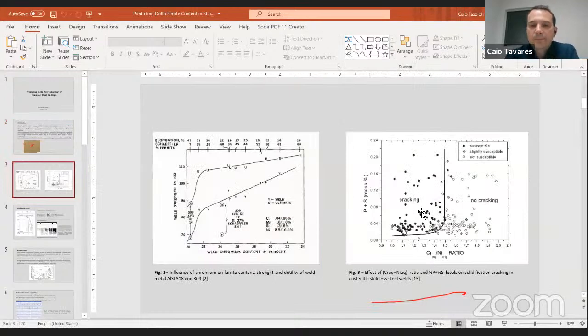Because look at this graph, which tells about the susceptibility to have hot tears. There is phosphorus and sulfur in the composition. If the amount of those tramp elements is not very low, if you have just a little bit of those elements, you may have cracking. And when you have the delta ferrite, those elements are dissolved in the delta ferrite, which minimizes the susceptibility to get cracking or hot tears at elevated temperatures.